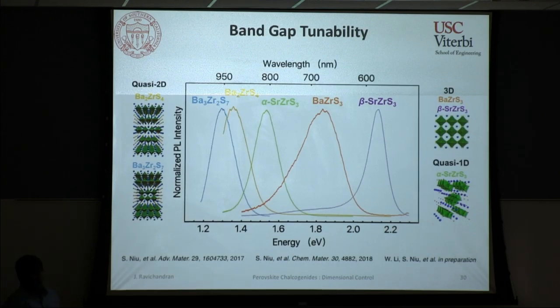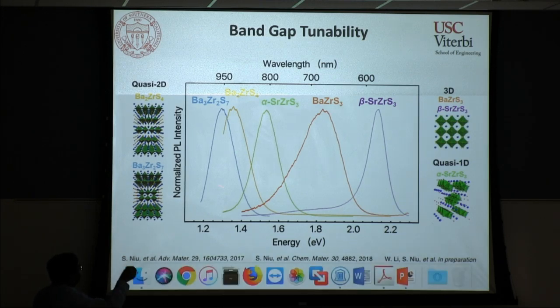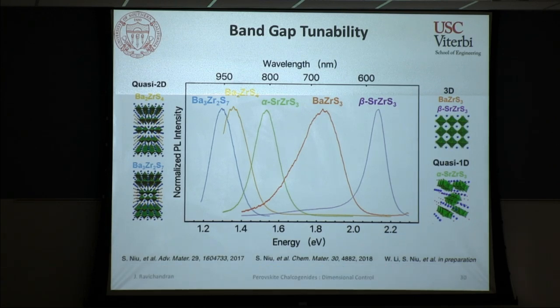So let me summarize all the luminescence curves from the various compounds that I've shown here. These are materials that span all the way from the green gap, which everybody is interested in for light emitting, down to the single junction optimal solar cell gap. So we have shown that these materials have luminescence at wavelengths relevant for technological applications. The next step for us is to show that we can grow thin films of these materials, make some devices, and show that they do work very well. So that's the first half of the talk.